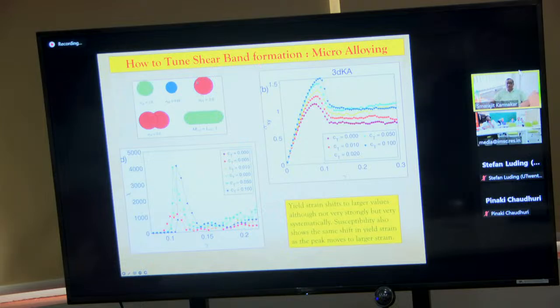This is demonstrated in this figure in the top left corner on the right. We took particles which are of diameter twice, and we just changed their concentration. We do see that the yield point moves to larger strain, so it has some pinning like effect, but it's not fully what you can get in a random pinning. But it produces some effects which we feel is a signature of a pinning like effect.